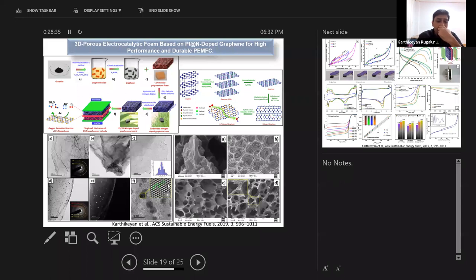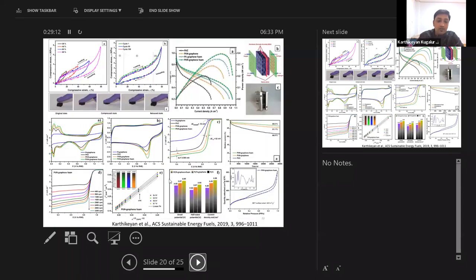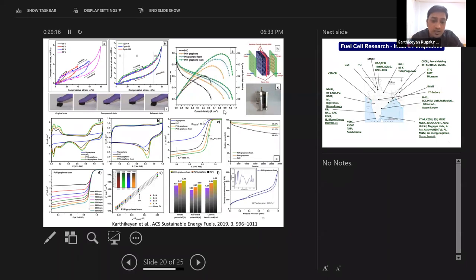We have also fabricated the same thing with graphene foam. Initially the graphene is derived from graphene oxide, and the graphene oxide is basically derived from graphite. The graphite is converted into graphene oxide using Hummer's method and it further converts into graphene by a chemical reduction method. So this graphene is deposited onto the commercial polyurethane foam and it is heat treated and finally converts into graphene foam, which was used for the purpose of catalyst layer development. And this has also been tested with several characterizations and we have identified an improvement in the efficiency. But compared to this graphene foam, we have identified that the mesoporous carbon nanofibers were showing higher performance.